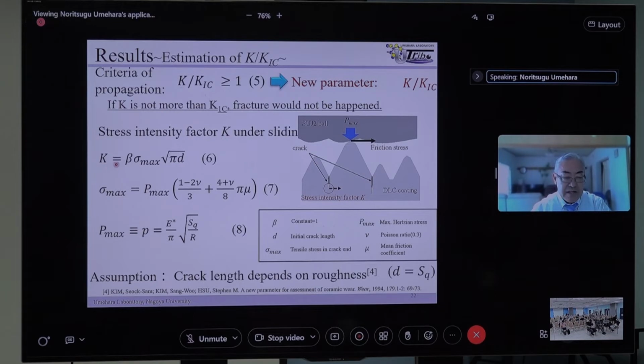The stress intensity factor K can be described like that. Sigma max is the tensile stress in the cracks, and D is the initial crack length, the pre-crack length. So if we can estimate sigma max and the D value, we can estimate the stress intensity factor K on the surface. Such a way has already been developed by a good Korean professor, Professor Kim, who has published how to get the K value on the surface.